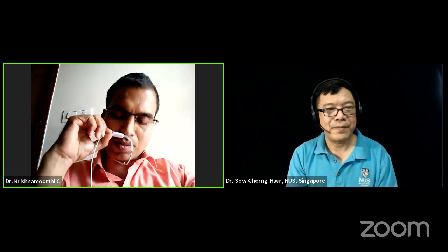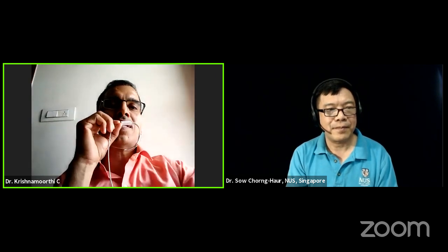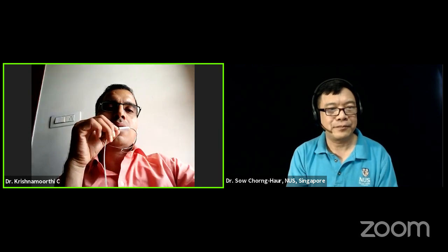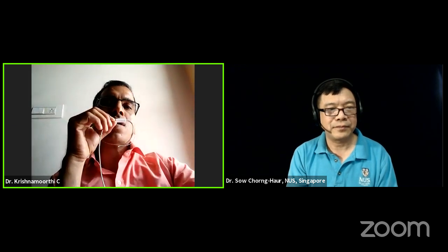And last question, please. Yes, the as-grown WS2 samples have shown fluorescence only at the edges. So when you irradiate the sample, it is shown in the interior of the sample also. Do you think at the edges only, during the growth, you have oxygen? Yeah. So I think we have reason to suspect our growth chamber. Typically we use silicon dioxide over silicon as our substrate. So that is one source of oxygen supply.